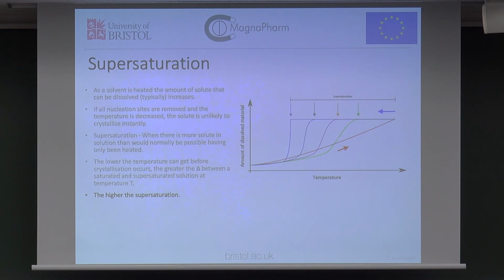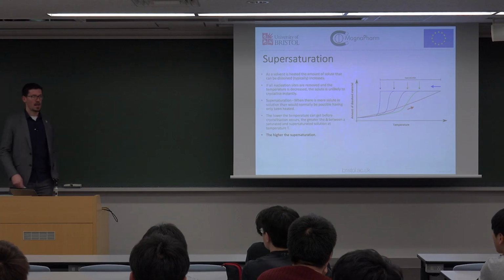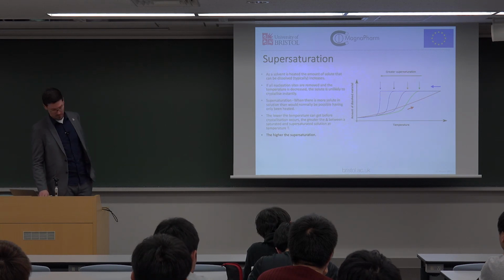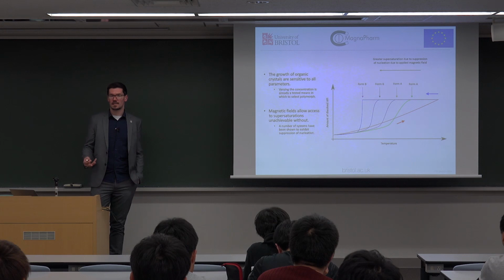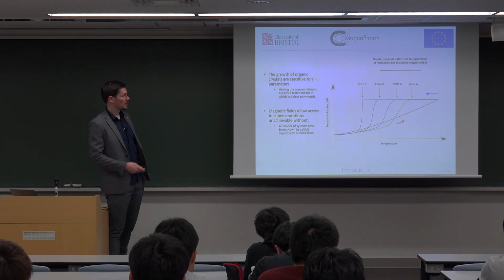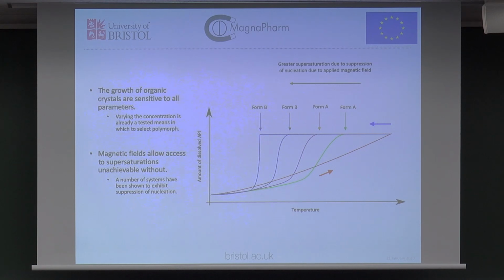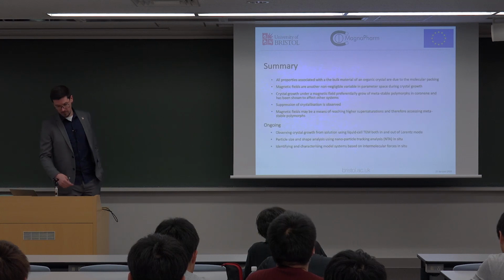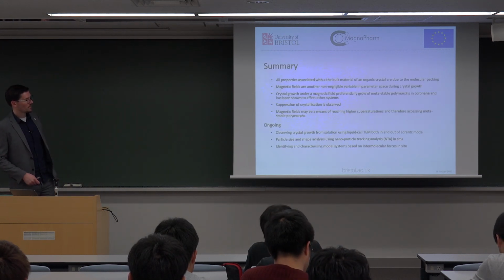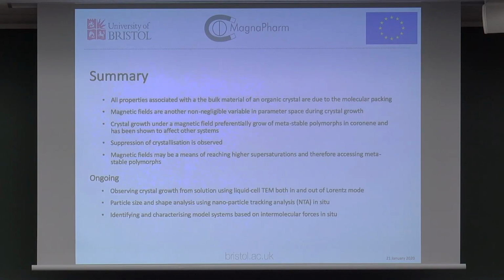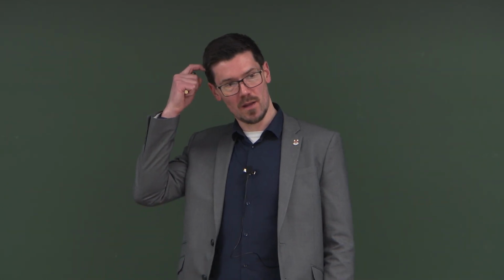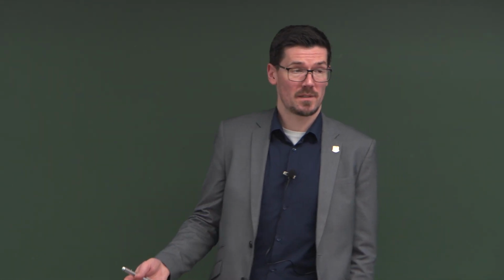So it has a greater supersaturation than this, okay, which is important because it's probably where the selectivity of the polymorphism lies. So we get form A at lower supersaturations, form B at higher supersaturations, and the magnetic field is allowing us to access these higher supersaturations. So to summarize that, all properties associated with a bulk molecular crystal are a function of the interactions between molecules. You change those interactions, you turn a molecule over, things change. Any property can be affected by this.